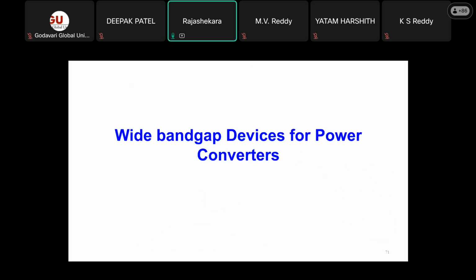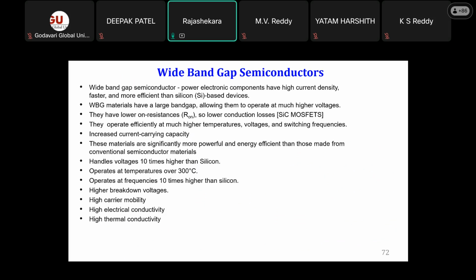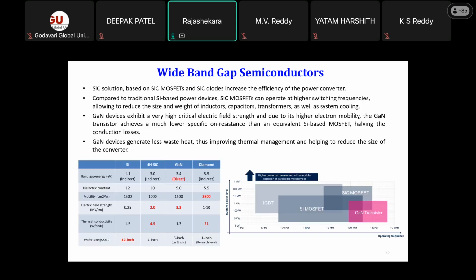Then we'll talk a little bit about the wide band gap devices, which I mentioned earlier. Wide band gap semiconductors are silicon carbide and gallium nitride right now, because they have higher thermal conductivity, can operate at higher temperatures, and have higher breakdown voltages, higher mobility, and high electrical conductivity, everything, when compared to silicon devices. They also have a low on-state resistance when compared to silicon MOSFETs. This gives an idea about the band gap. Silicon is 1.1, whereas silicon carbide is 3.0 electron volts. Gallium nitride is 3.4, and diamond is still not being used, but ultimately people are thinking about it, though it will be quite expensive.